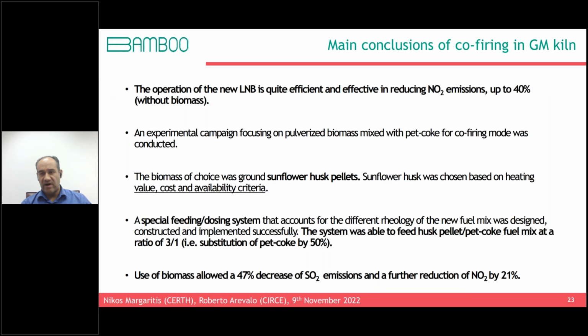So the main conclusions of co-firing in the GM kiln: the operation of the new low NOx burner was quite efficient and effective in reducing NOx emissions up to 40% without biomass. An experimental campaign focusing on pulverized biomass mixed with petcoke for co-firing mode was conducted. The biomass of choice was ground sunflower husk pellets, chosen based on heating value, cost, and availability criteria. A special feeding dosing system was necessary in order to handle the new fuel and not to have blockages in the production process. And with this new special feeding dosing system, a 50% substitution of petcoke was realistic.